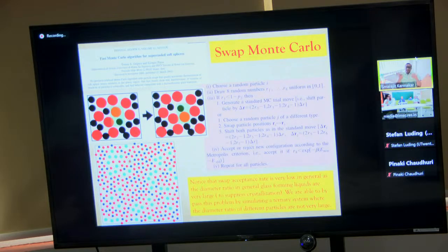One can easily see the difficulty. In a dense environment, a smaller particle can easily be placed in the position of a bigger particle, but the bigger particle cannot be put in the place of a small particle because it is going to overlap with the other particles. This will be energetically very costly, so the moves will be very, very rare. In binary mixtures, the acceptance rate sometimes goes to 10 to the minus 5 or 6. But surprisingly, even with that small acceptance rate, the dynamics can be sped up significantly.